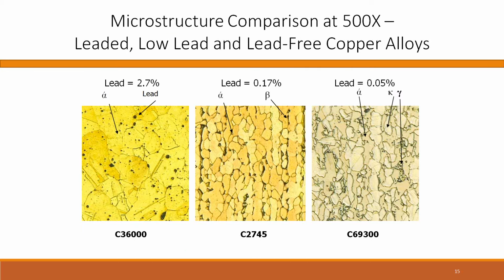The differences between these different alloys microstructurally are shown on the left. And you've got 360 alloy, which is the alpha phase that we talked about, the copper and zinc, and then the lead particles that are in there to break up the turnings. The 2745 alloy that's in the middle doesn't have any lead in it, and it uses microstructure like the grain size and these beta phase particles that are kind of prone to corrosion, but they help break up the chips to some extent. The right-hand microstructure is for the 693 alloy, which is the combination of copper, zinc, silicon, and phosphorus. And that has 3 different phases in it that have different hardnesses, and they help break up the chips during machining. If you want to go with an alloy that contains bismuth or sulfur, it looks a little bit more like the 360 microstructure on the left-hand side.